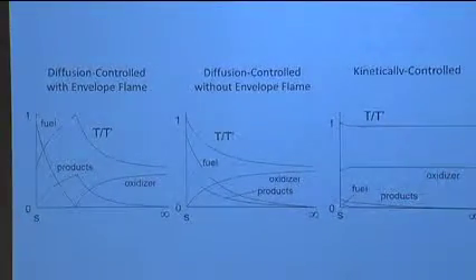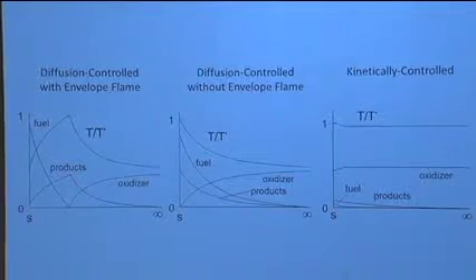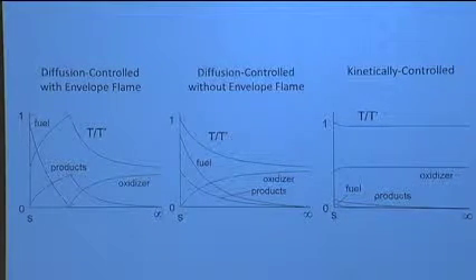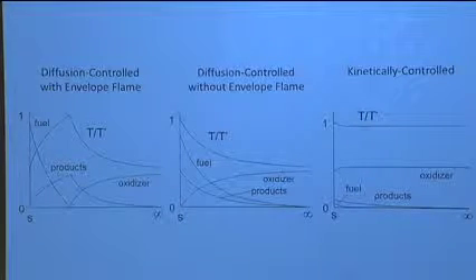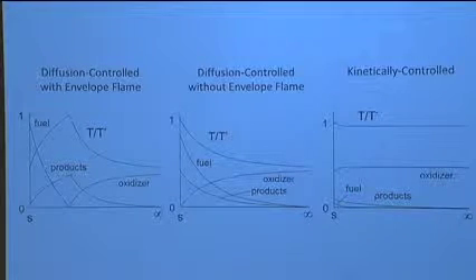Whereas in this region over here, where the particle's burning, if this was aluminum, this flame temperature out here is 4,000 K, and it's this temperature that has the biggest influence on how the particle's burning. So it's really the flame temperature. Here, since I don't have any localized reaction out here, it's really the environmental temperature.